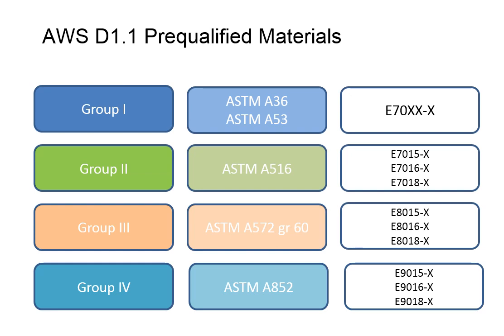Then we get to group 4, and there's only like 3 metals listed as being pre-qualified for group 4 in clause 3. ASTM A852 is one of them. You can use the 90 KSI materials with that. But once again, you're going to have a little higher preheats. These are a little more temperamental than even the group 2 materials. So you've got to tread with care when you're welding in this zone of the universe. So just something to keep in mind.